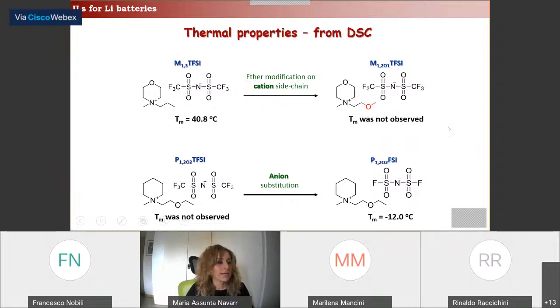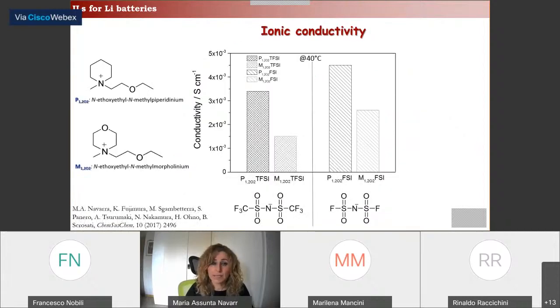These new ionic liquids were also tested in terms of ionic conductivity, of course, and slightly higher conductivity values have been obtained with the FSI molecules. This, of course, is due to its higher mobility and lower viscosity, and acceptable values to be used as electrolyte in lithium cells were obtained. Also, when the lithium salt was added, the lithium transference number was considered to be reasonable for practical application.